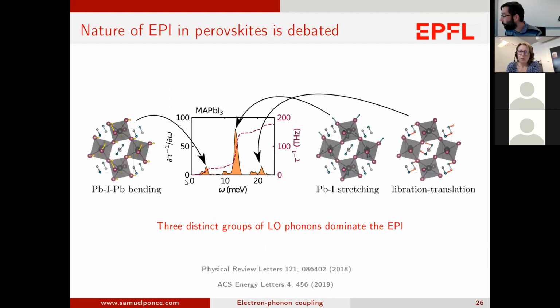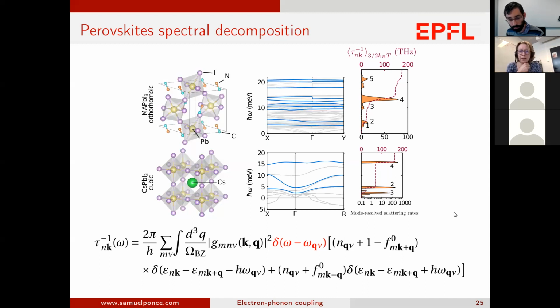Samuel, may I have a more simple question related to the comparison between MAPI and cesium lead iodide? You said that in both cases you have three phonons involved, and the one highest in energy for MAPI is related to the libration of the molecules. What is the corresponding phonon in cesium lead iodide? So 4 is the dominant one, and this corresponds to 4 here. 5 is the libration, and it's not present in cesium lead iodide, like you mentioned. In MAPI we have 5 more or less. And so the 2 is corresponding to that one, and then the 3 is corresponding to that one.